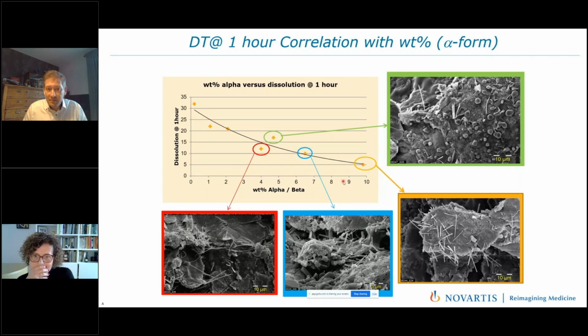This has been remarkable because up to now, the way you are able to do a quantification in a physical mixture of forms is either to do some Rietveld measurements or some spiking experiment in order to understand the extent of the content of the other forms. But here, one has to keep in mind, and I apologize, I forgot to mention it, that we are dealing with a drug product which contains plenty of other excipients.